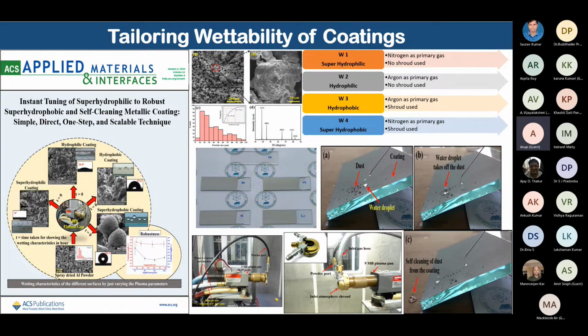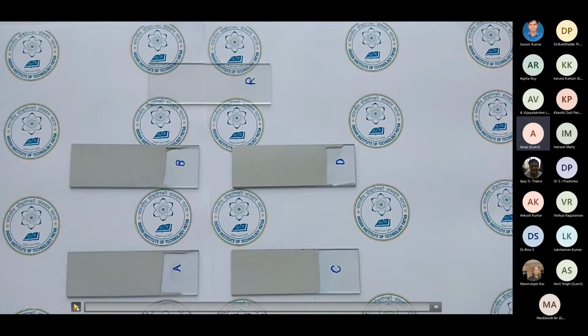So what we have done is take aluminum metallic powder and coat it over the glass substrate, changing the process parameters in such a manner that with the same powder we should be seeing different kinds of wettability. Now let me show you a very small, 30-second video on this. You are able to see here the four samples A, B, C, D. These are aluminum coated over the glass substrate, and R is the bare glass substrate, right?